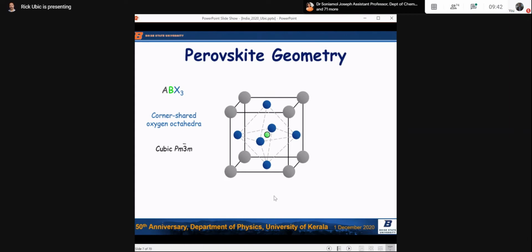That's one unit cell. If you put several together, you can see they're going to share corners, vertices of the octahedra. And they're going to contain one B site in there. And if you connect up a lot of octahedra, inside the octahedra you're going to have one A site that'll be 12-coordinated, cuboctahedrally coordinated to the oxygens around it. And those are the ingredients for perovskite. In the cubic form, it's space group Pm-3m.